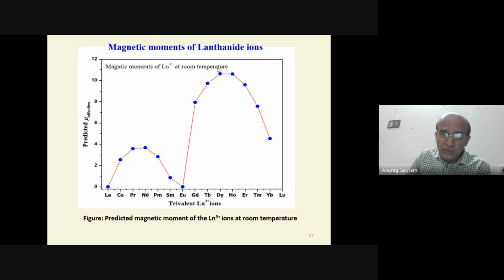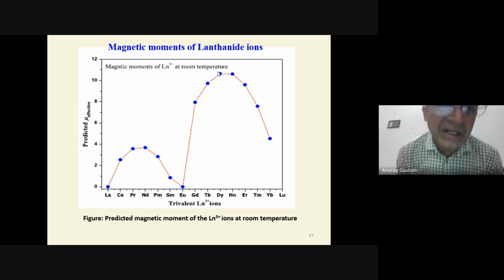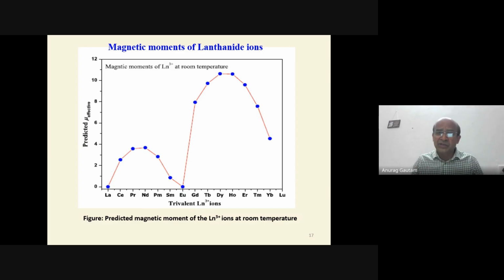But for T2, the overall magnetization is used: how many emu per gram there are, how many total magnets there are. Because for gadolinium-based contrast agents, or any material which is T1 based, we said that only surface atoms contribute, because they are close to the surface, and the water molecule has to come to the surface and get relaxed.